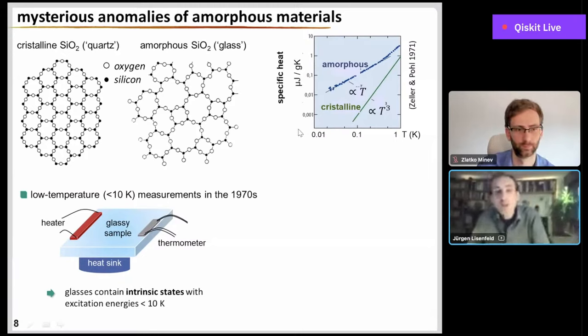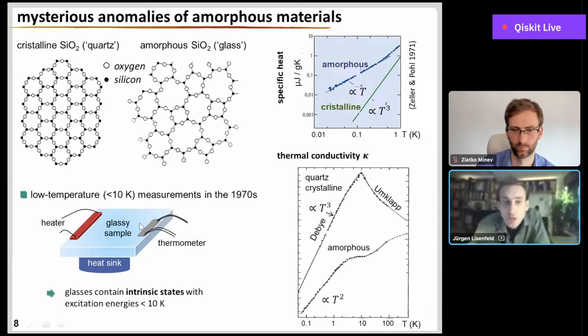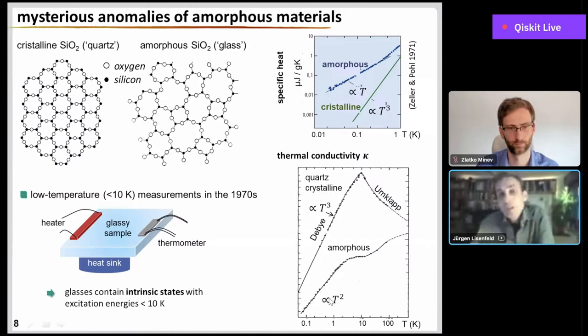And there's another experiment which you can do with this setup. You can, for example, measure how easily the energy travels from your heater to your thermometer. This is the thermal conductivity. And you see that the amorphous material has a much higher resistance towards this heat flow, probably because of the scattering centers, which are related to these intrinsic states here.